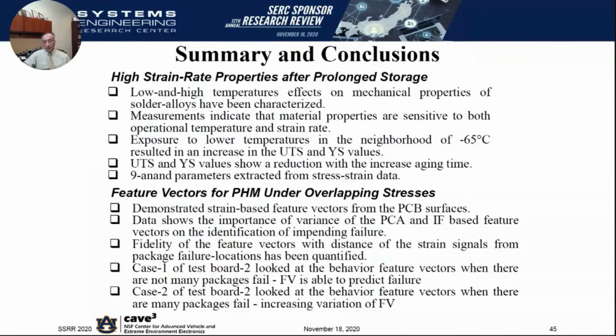So what we have done is we have shared with you data on 2 subtasks. The first one being high strain rate properties after prolonged storage, where we shared with you data on a number of different advanced lead-free alloys at high strain rates in the range of temperatures of -65 to +200 degrees centigrade, and we shared with you a method to actually model the constitutive behavior using a non-viscoplasticity. We also shared with you how the model would be implemented for assessment of the transient dynamic behavior of board assemblies in harsh environments under overlapping stresses of temperature and vibration, and we showed how to create the hysteresis loops.